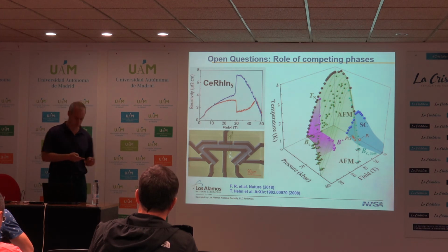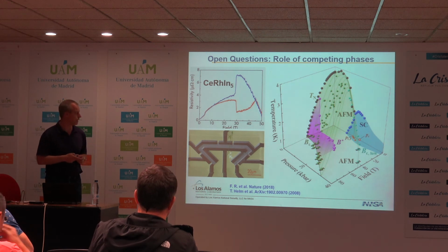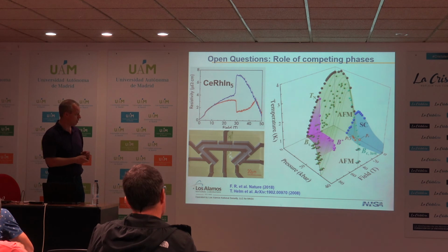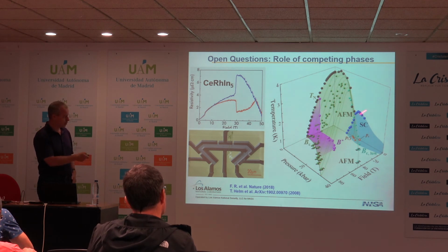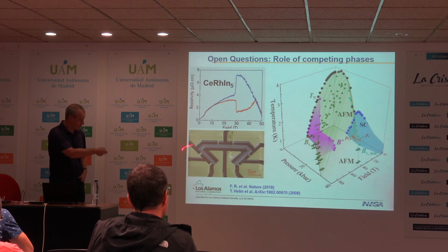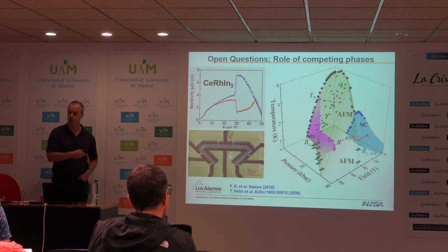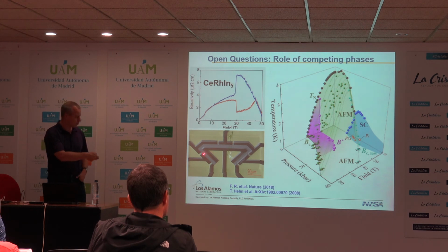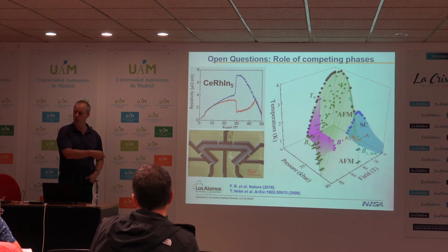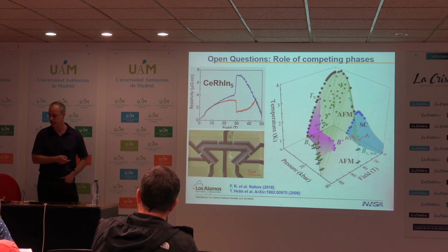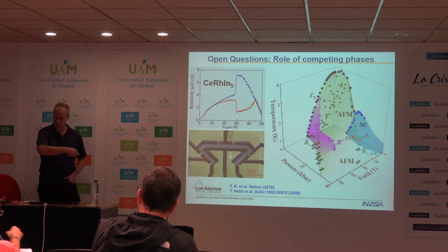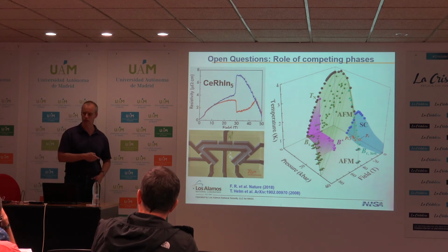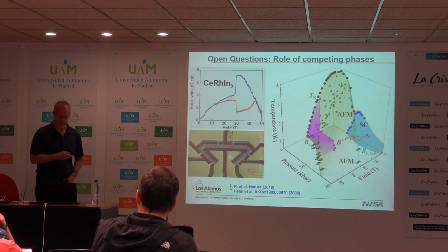Yeah. Can you see superconductivity? Yes. So you have the situation where the resistance falls to zero, in this structure under pressure, and we've also done similar ones on the cobalt, and you see very clearly the superconductivity there. In fact, we're hoping to do critical current measurements on the FIB structures. Haven't found anything interesting.